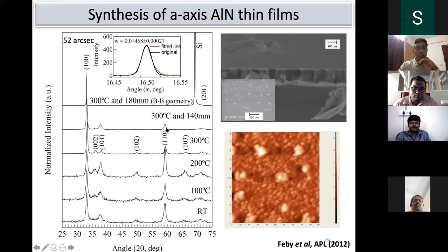this 110 peak also decreases, also the 002 and 101, the intensity decreases. But when I further increase the target to substrate distance, around 180 millimeter, interestingly, only one peak. And please mind here, all these profiles are from grazing incident XRD.